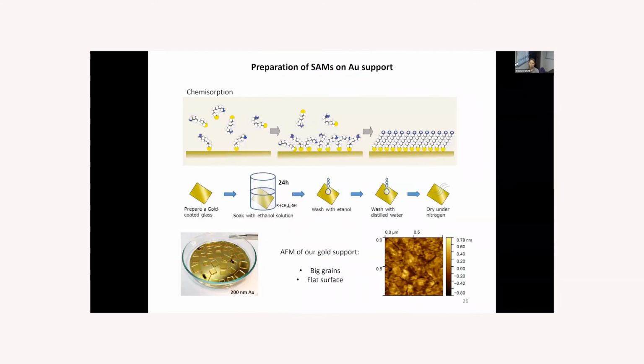How do we prepare the SAMs? We prepare them on the gold support, which is a 200 nanometer gold film deposited on top of glass. We soak the glass in the ethanolic solution of the selected alkanethiol for 24 hours. Then the adsorption of the molecules occurs, and they order in a very crystalline manner over 24 hours. After that, we wash the samples with ethanol and dry with nitrogen, and we obtain our SAM monolayers. Our gold supports are very nice flat surfaces with big grains, which facilitate the formation of well-ordered SAMs.